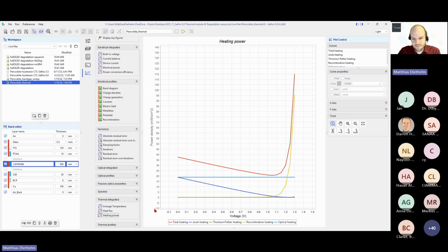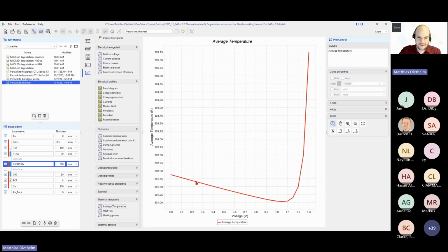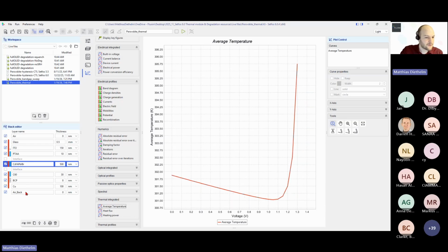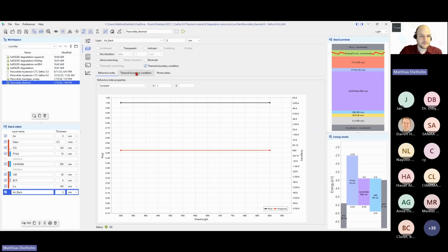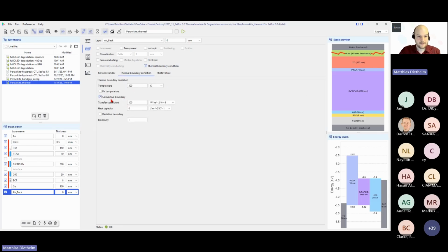What's important now is to understand how this heating power is translating to actual cell temperature. So in the model I chose here, you can see that this power translates only to a minor temperature increase from 300 Kelvin, which was chosen as a rough room temperature environment. But that's because, and now we are looking into some of the parameters of the thermal model, if we go to the boundary condition, which is set up as a convective boundary, so you have airflow, for example, this parameter here, the transfer coefficient of 100 watts per square meter and per Kelvin, represents a very strong airflow.